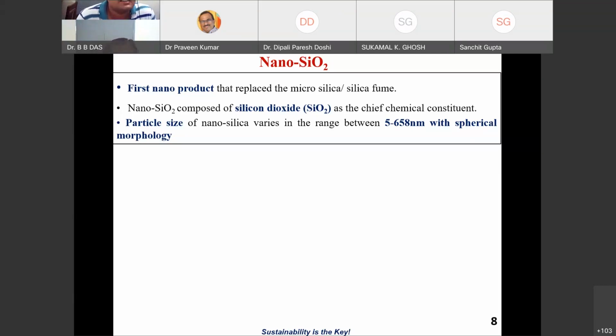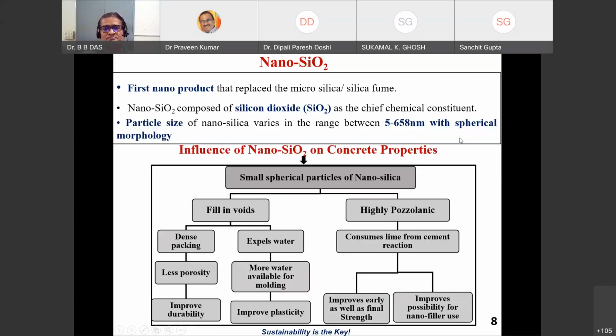So let us go to the nano silica, that is nano SiO2. Now, when I talk about nanoparticles, there are many types of nanoparticles. But for concrete technologists, for civil engineers, we know nano silica, that is nano SiO2, is the best one, because it is siliceous and I need a siliceous material. The first nano product that replaces the microsilica or silica fume is nano SiO2. Now nano SiO2 is composed of silicon dioxide as the chief chemical constituent. We need silica because I have plenty of calcium with my cement. And particle size of nano silica varies from 5 to 658 nanometers, with spherical morphology.